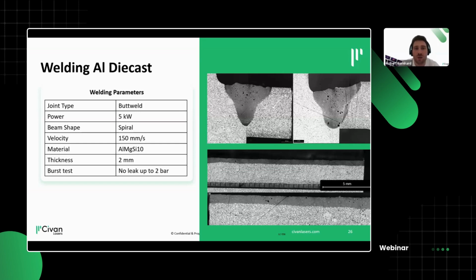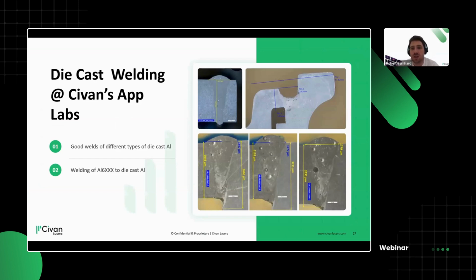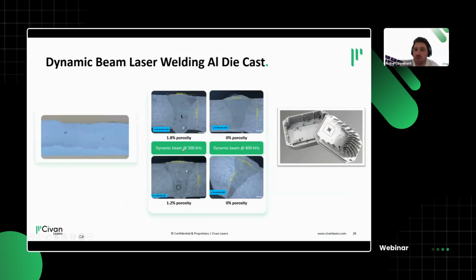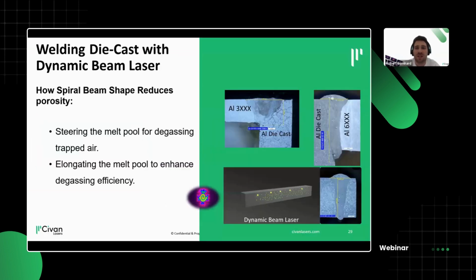And doing this with the laser with our dynamic beam shaping, in terms of the dynamic spiral, we get the opportunity to remove the porosity out of the welds. And then you can also start playing with the dynamic beam shaping frequencies. But for die cast, I would argue it really depends also on the die cast quality what you can achieve. So maybe 0% porosity is a stretch, because the base material has some porosity, but at the same time, I think there are ways of melting and degassing these materials at the same time.